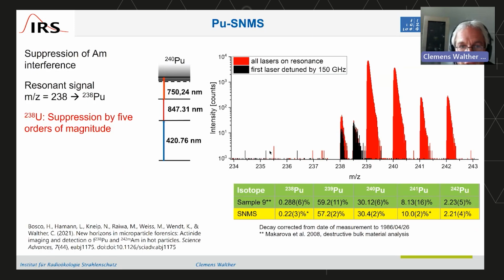Then you switch on the laser and you tune the lasers to the plutonium resonance, so only the plutonium is ionized here. That gives you a number of peaks: 238, 239, 240, 241, 242. The 238 is a bit critical, as I told you, because we know now that the particle is composed mainly of uranium-238, and there is only a minute amount of plutonium.